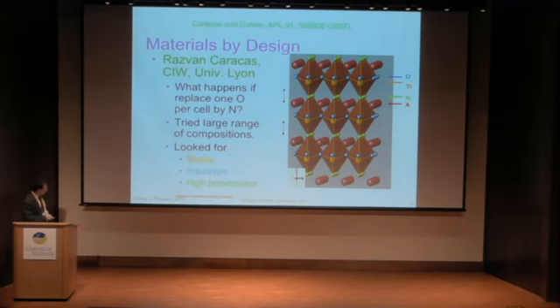This is work that I did with Razvan Caracas, who was a postdoc at the time, and we made some predictions based on a perovskite structure like this, where you replace 1/3 of the oxygens with nitrogen. So you make an O2N oxynitride. The question was simply, what happens if you replace an oxygen with a nitrogen? It's very easy to do on the computer. On the other hand, it's still a lot of work because we went through a large amount of the periodic table, and we had some criteria.